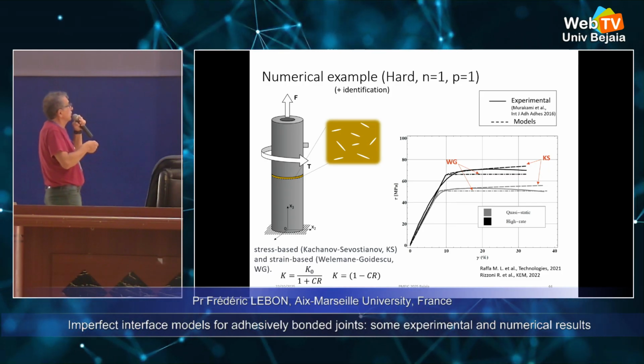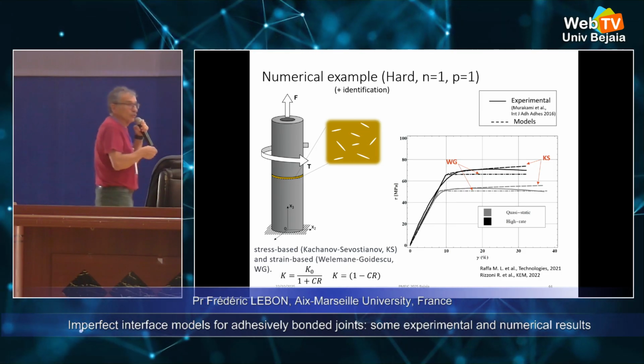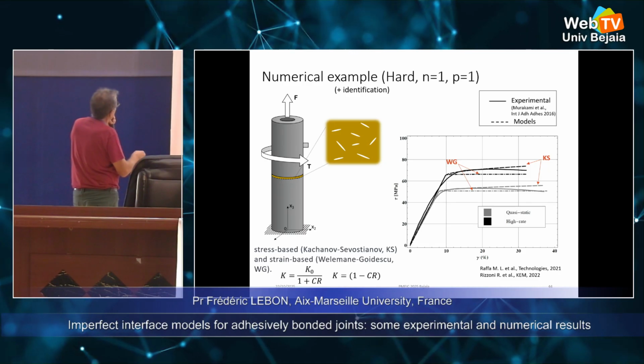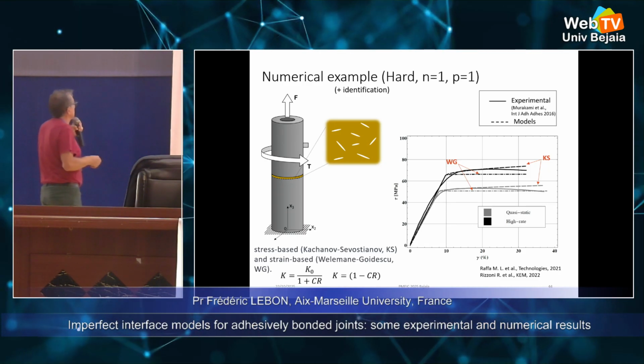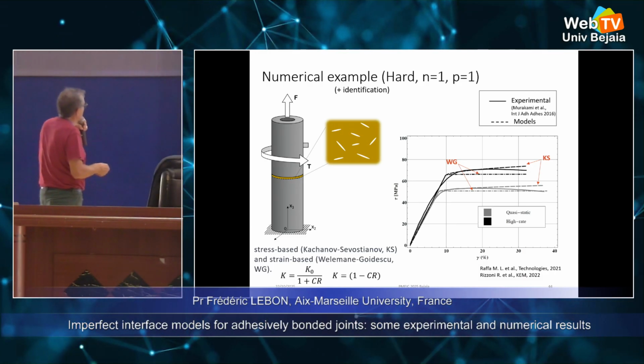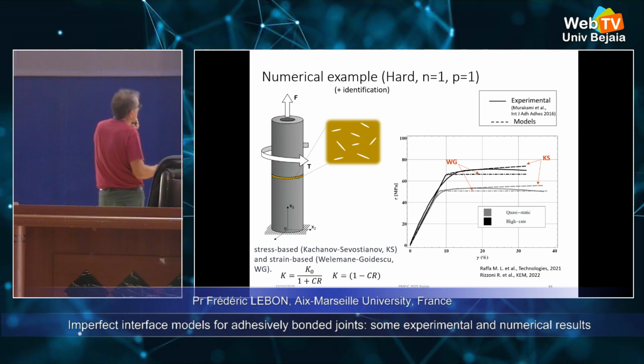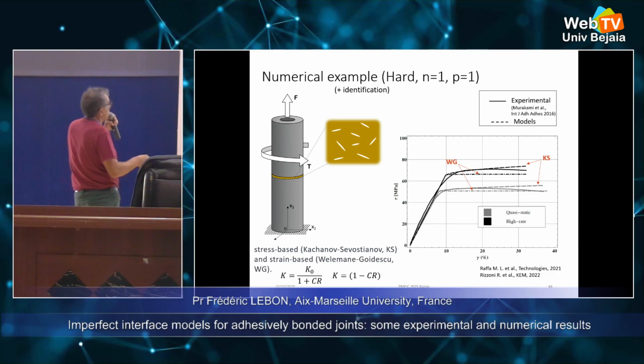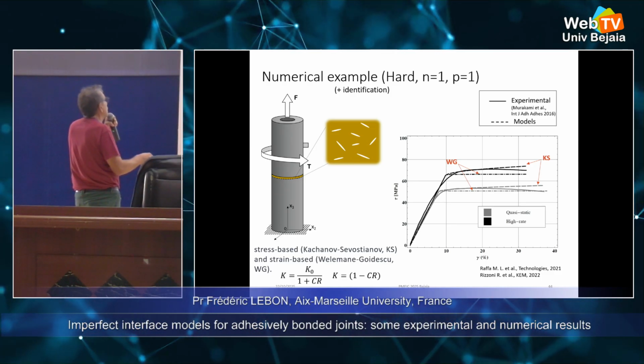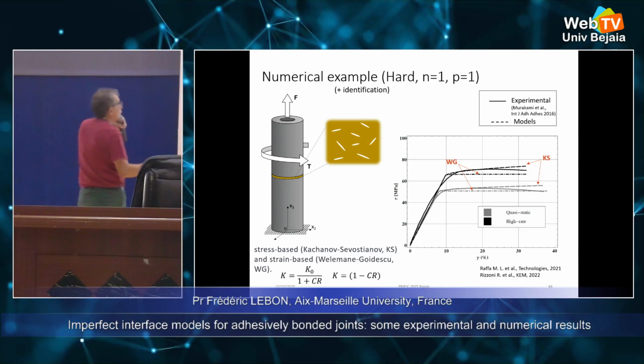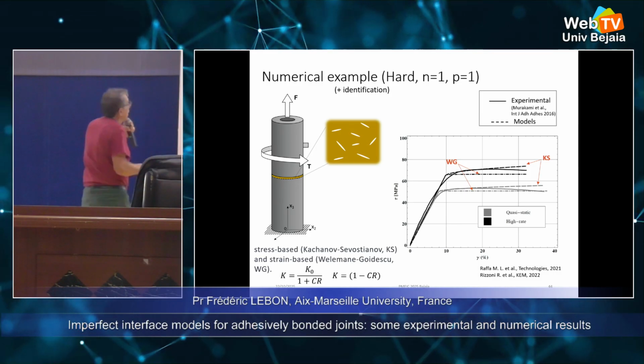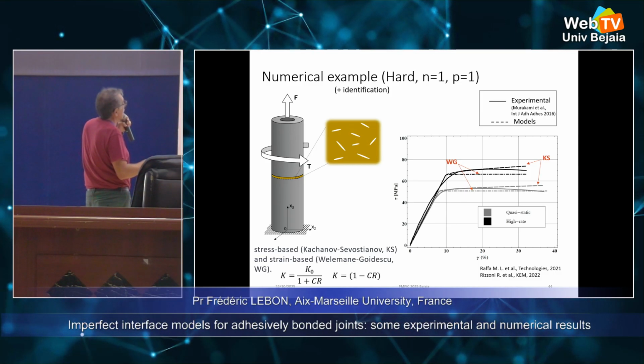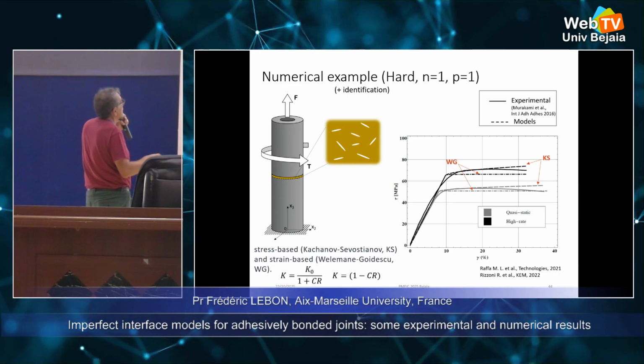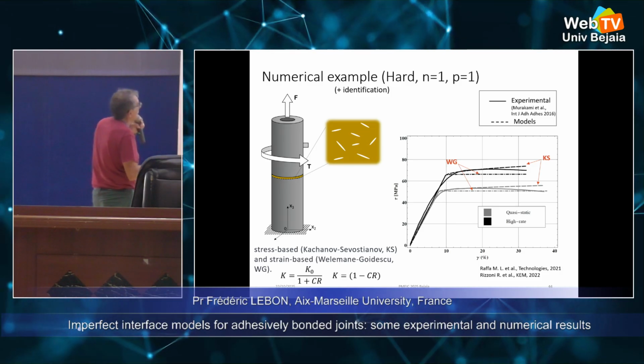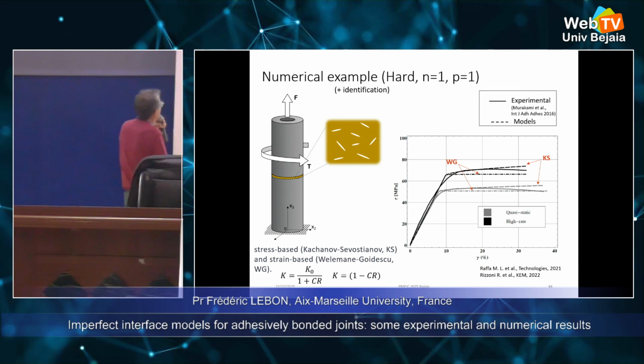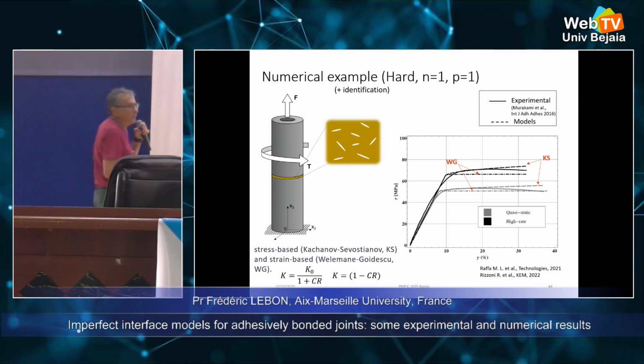It is an example in torsion and traction together. Okay, we have a tube. The two parts of the tube are bonded by a glue, and we have a torsion and a traction. And you use two kinds of model to introduce micro cracks. There are two possibilities, at least two possibilities, and we can compare the evolution. In fact, here we have the shear stress, and here we have the shear strain. And we can compare with the experiment. The experiment is in black, okay. And we have the two models we use here for two rates of loading.